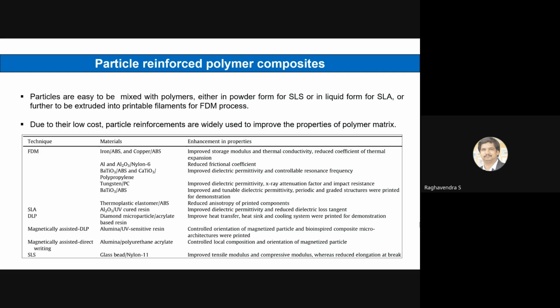That is where we are going to the next step of FDM, where with particle reinforced polymer composites you can make functionally graded materials, which was not earlier possible in FDM. One example you can see is the first one, iron and copper particles. If you add these, it will solve your distortion problem in FDM. Why? Because in the latest research it has been observed that by adding these particles to ABS specifically, there is a reduction in the coefficient of thermal expansion. Thereby the thermal distortion that was there is straight away removed. So that is one advantage.